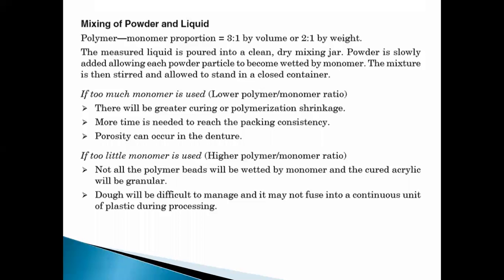So what will happen if there's too much monomer? Polymerization shrinkage will be more. Packing consistency would not be good when you'll be trying to pack it into the mold. It will be very thin, sticky. Okay. So you won't be able to handle it very easily. What if the monomer is too less? All the polymer won't be wetted by the monomer. So the mix will be too granular.